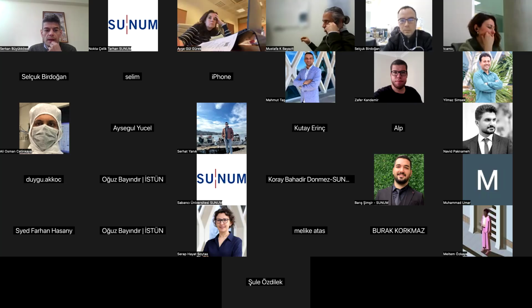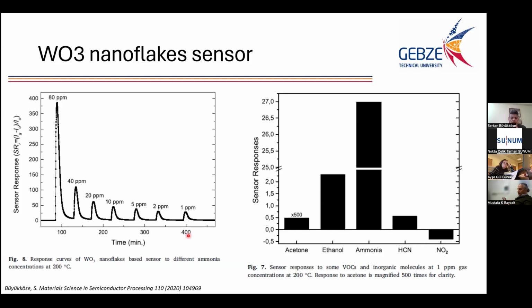And if you look at the measurement results, with this structure we were able to measure ammonia even at the 1 ppm level. Here you see the response of our sensor from 80 ppm to 1 ppm against ammonia, and even at 1 ppm we see a very clear signal. Also on the right hand side you can see the comparison with interference gases. Here the interference gases are chosen as acetone, ethanol, HCN, and NO2. They all exist in human breath. So it seems that tungsten oxide nanoflakes are quite selective against ammonia at low concentrations.